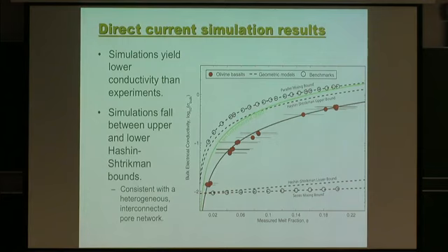So what we see is this, a log-log plot of conductivity versus the measured melt fractions, right? All the dots are where we calculate the electroconductivity, and you can also fit a power law there. But this actually has a similar shape, but has some absolute value discrepancies from one of the measurements by Ten Grotenhuis, right, in 2005.